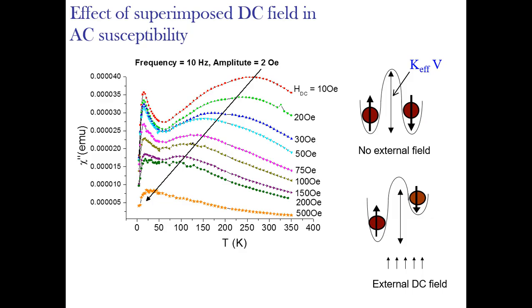because we have forced the particles which are along the field axis to remain in the field axis, and there is no jump in the other direction. But the spin glass peak remains unaffected, which is due to its metastable state, and the two-valley anisotropic barrier picture is not valid. We have an energy landscape of energy barriers.